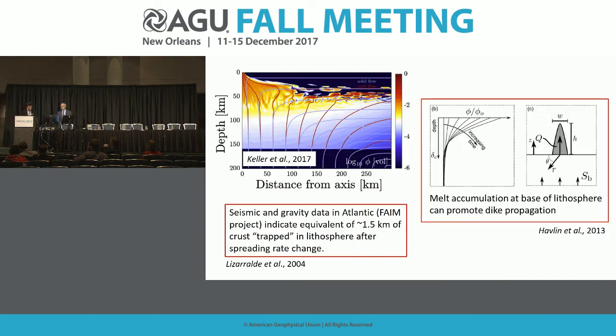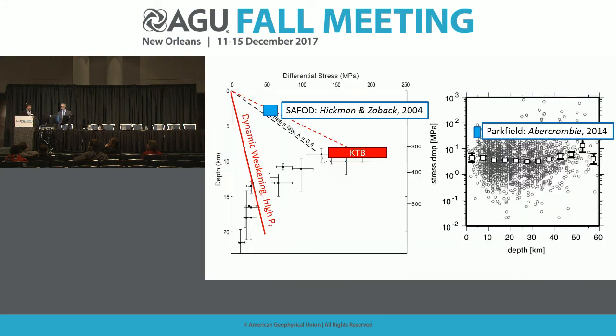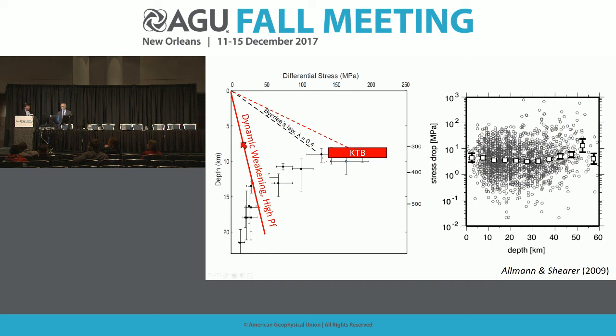Yeah, it's a good question. So everyone close your eyes. What Lars is saying is I put this cool red line in here, and one of the things that does is it chops off this higher stress viscous portion of the brittle ductile transition. One of the very key aspects of the dynamic weakening process is that it requires frictional slip on a very narrow shear zone. Over the million-year time scale, you wouldn't predict strain localization into a centimeter-wide zone by the power law creep mechanism. So the trick around the conundrum you're developing is that we could have a higher stress viscous region and then a relatively quick drop off to this dynamic weakening type of stress profile.